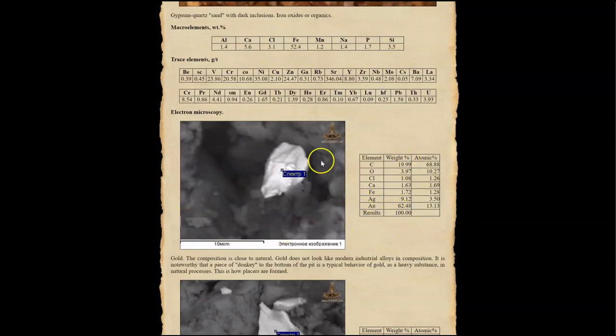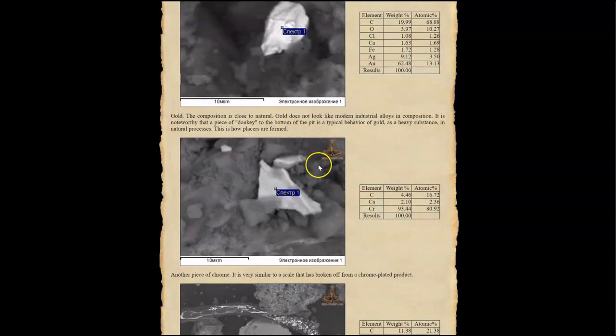And here is a very interesting microparticle of gold, 62.48% gold and 9.12% silver with 1.72% iron. So this is almost pure gold, described as having a natural composition, not reminiscent of modern industrial alloys, and found at the bottom of the pit, which is natural for heavy gold deposits. Still another very interesting find in these samples.